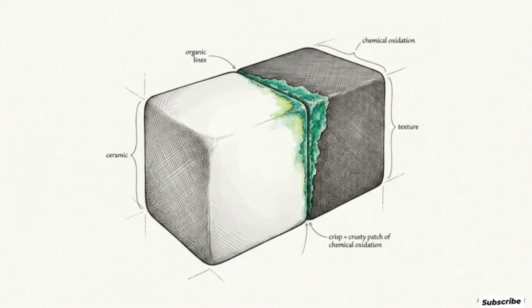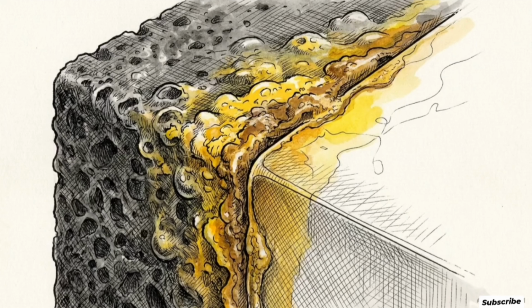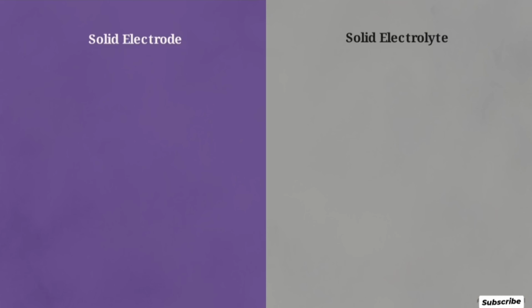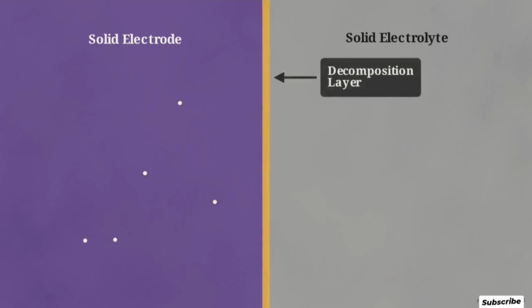Even if the structure stays intact, a quiet chemical conflict is happening. Many solid electrolytes, particularly sulfide-based ones, are highly reactive when touching lithium metal. This cross-section shows the interface where these materials meet. They react to form a resistive decomposition layer, a space charge layer, right along the seam.